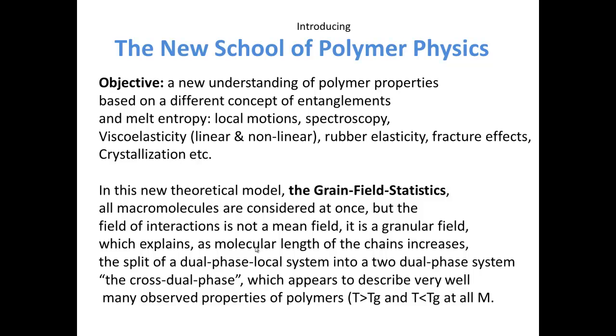And I am introducing a new model of interactions, of the van der Waals interactions, basically, between components of molecules, which I call conformers, and although the statistics is broader in scope, I'm applying it first to polymers, with grain field statistics. I'm considering all the macromolecules at once. In other words, all the conformers from all the macromolecules are defining the system, and I am granulating the system by not considering the field of interactions as a mean field. It is a granular field which explains, and I will show it, that the concept of M sub e is not inherent to the macromolecule itself, but arises from the interaction between the macromolecules through the grain field statistics.